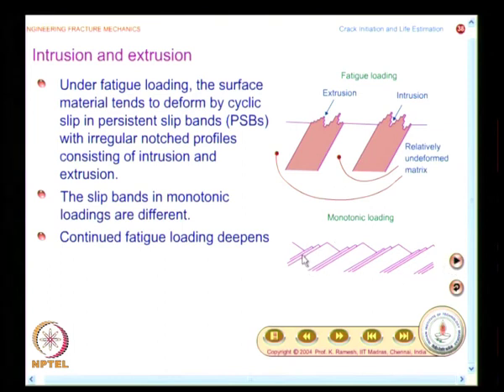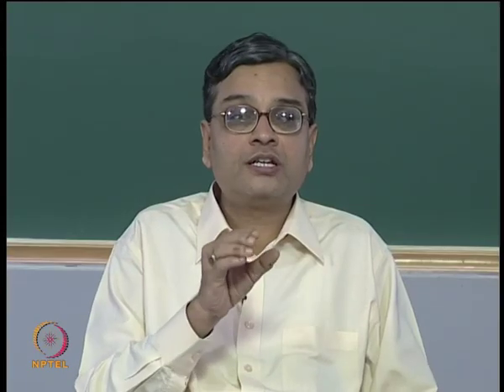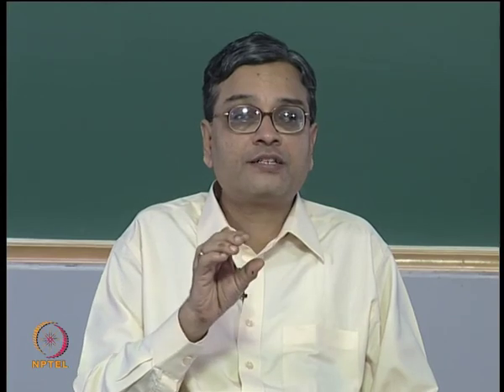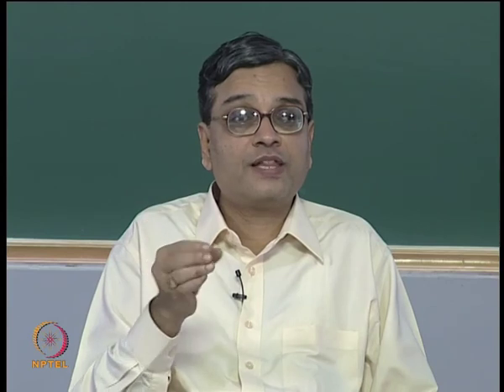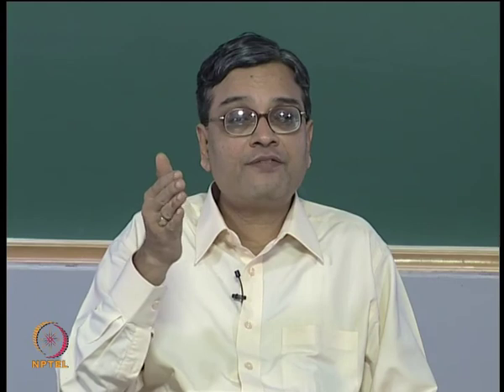In monotonic loading, the slip bands are like this. In the case of fatigue loading, you have extrusion as well as intrusion, and intrusion can eventually become a surface crack. People have shown evidence of that. So, that is why if you have a highly smooth fatigue specimen, its fatigue life will be more. If the surface is not very smooth and polished,